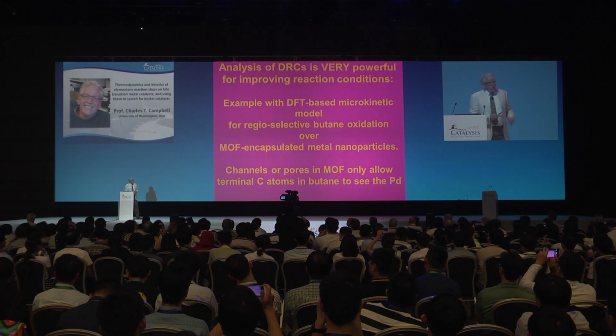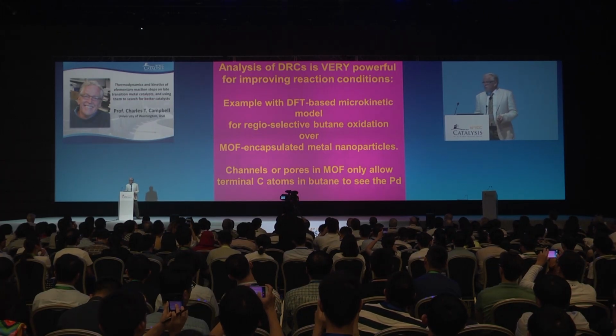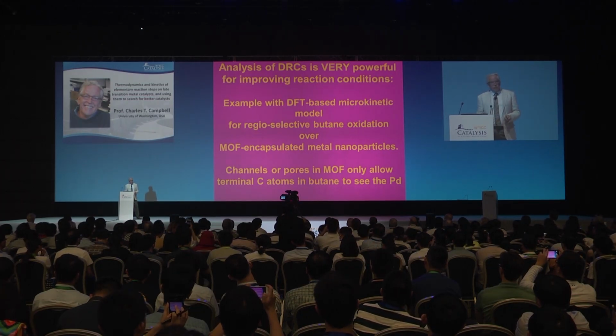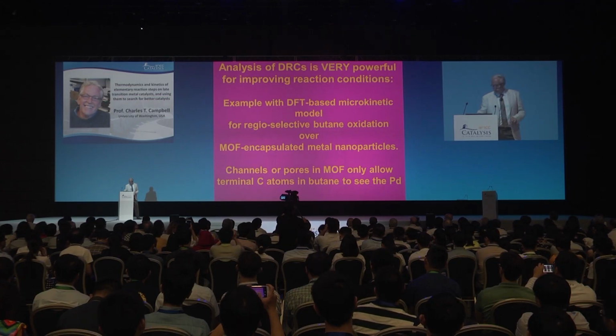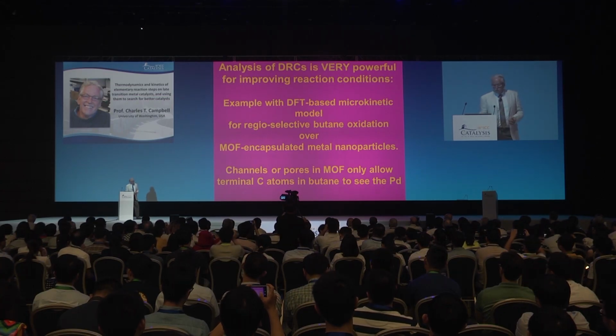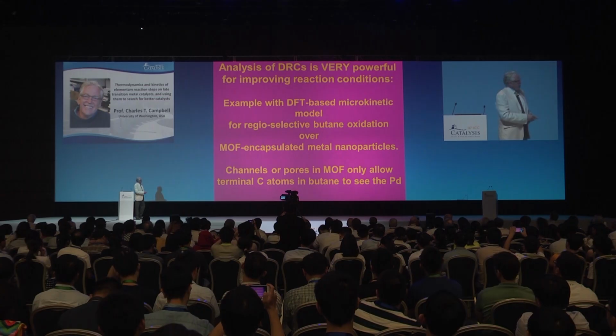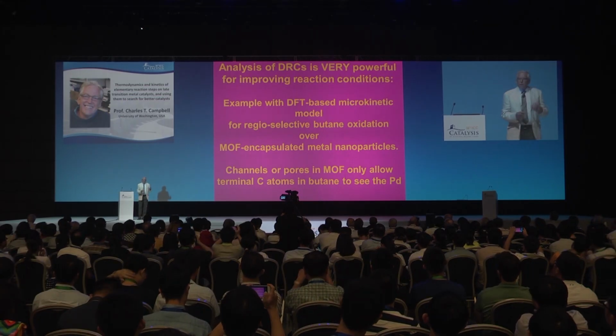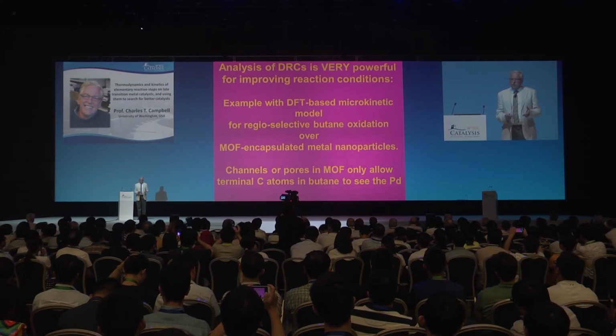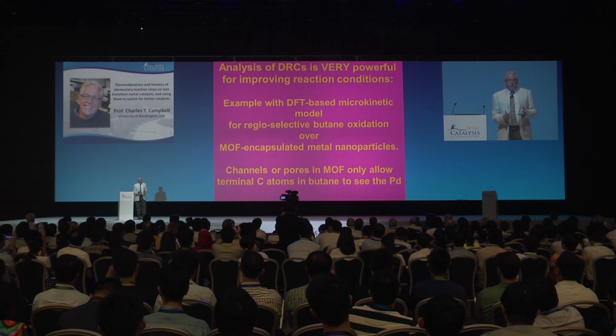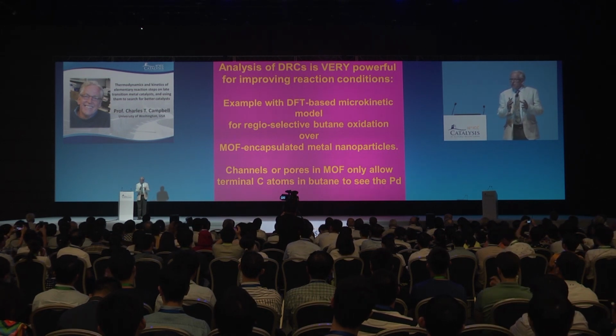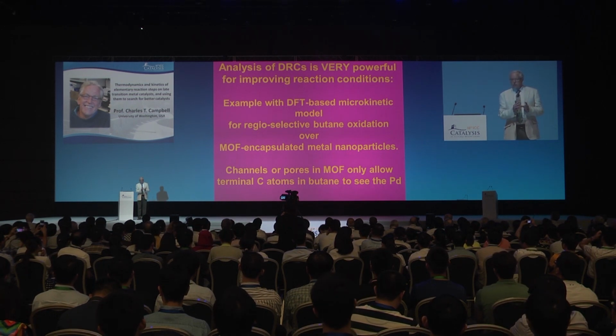And so it's also very powerful in analyzing how to improve the reaction conditions if you have a microkinetic model for a reaction. I'm going to show an example for a density functional theory model of MOF encapsulated palladium and palladium silver nanoparticles.